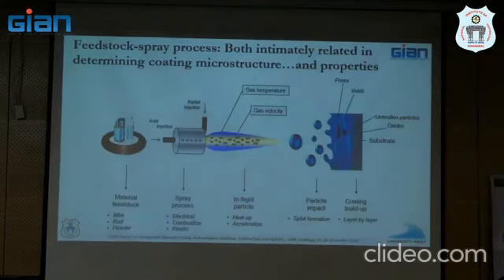All right. So let's come back to the same schematic in a slightly different way. Material feedstock, spray process. I said this is where the difference lies. How is the high temperature, high velocity zone created? There are typically three ways in which you create it. Sometimes it can be electrical. Electrical meaning you just strike an arc. You immediately create a high temperature zone. If you have two wires striking an arc, then you create a high temperature zone, and those wires themselves serve as material. And if you have a carrier gas, they take away droplets from that and form a coating. In some cases it is by combustion, this high temperature, high velocity zone, that is most common.